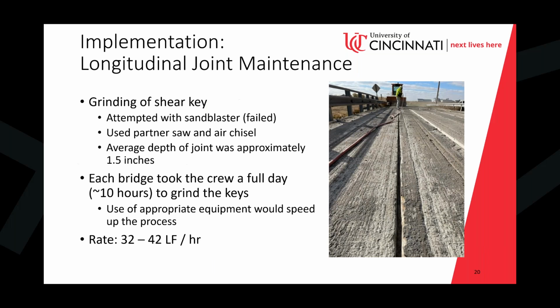So this involved actually grinding the shear key. We did not grind the full 3-inch depth that's shown in the previous slide. In this case, we just did the top 1.5 inches of that. This was done by a subcontractor. Essentially, they attempted first with a sandblaster. That did not work. They used a partner saw and an air chisel, which was ultimately what they ended up doing. But it was a tedious process.